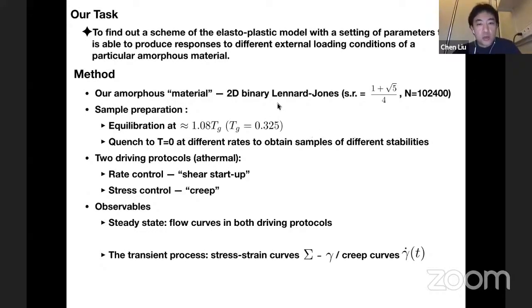And what do we do with these systems? We first equilibrate the system at a temperature that is slightly above the mode coupling temperature, where we are sure that the system is in thermal equilibrium. Then we quench the system to T equal to 0 at different rates to obtain different samples of different stabilities. And to each sample, we apply two driving protocols, which are athermal. The first one, we control the shear rate. This is the shear startup experiment. Then the second one is that we control the stress, which is the creep.